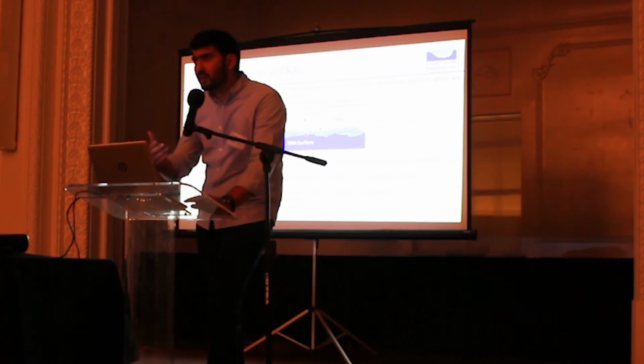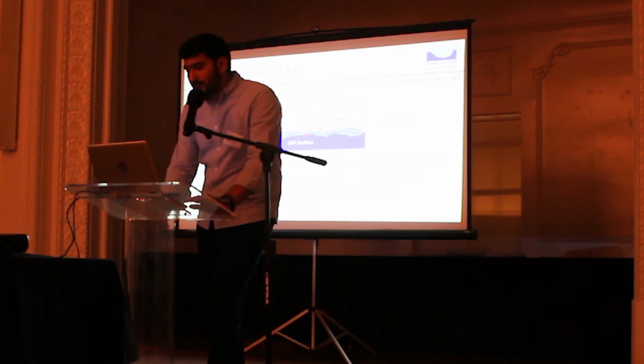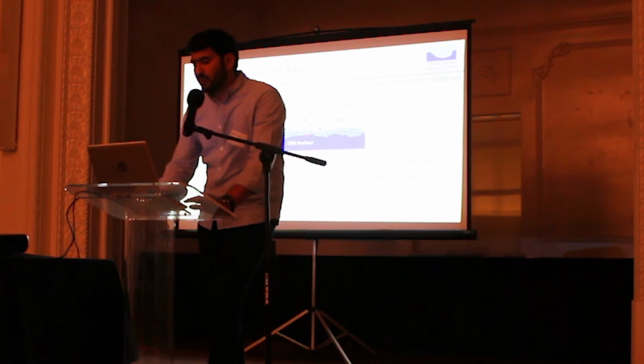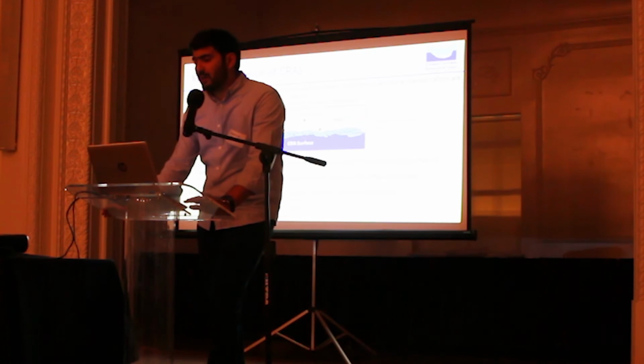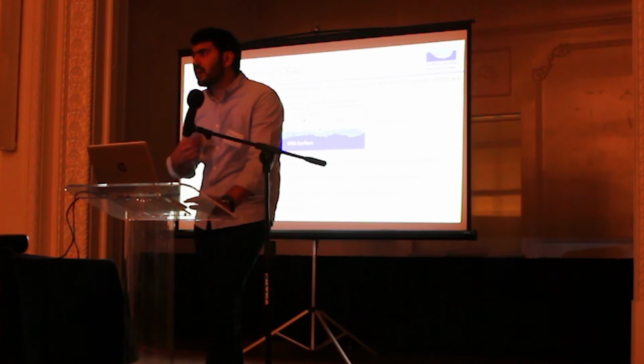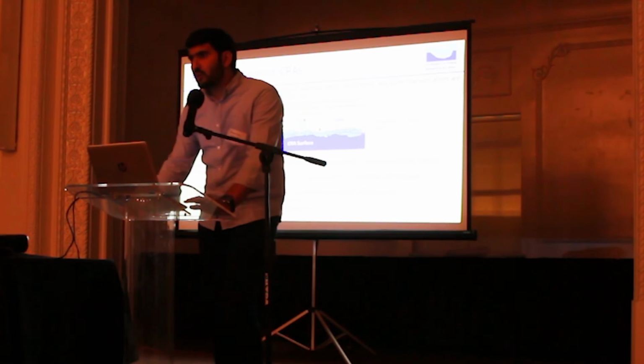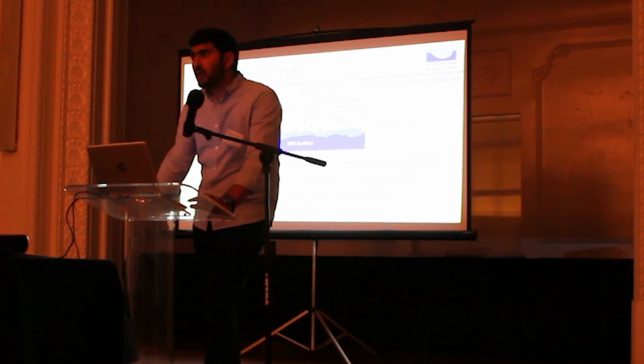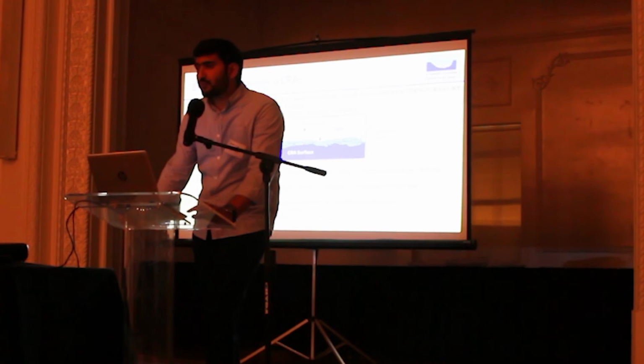In the presence of oxygen, there is a tendency for the passive layer, or the oxide layer, to repassivate and reform again while solid particle erosion is taking place, which suggests a synergistic effect between erosion and corrosion. In an oxygen-free environment, these oxide layers may not reform again. Also in salt water, we can have two competing processes happening at the same time. The chloride ion can break the passive layer, and the dissolved oxygen can work on the repassivation. So the question here is, is erosion corrosion a serious problem for CRAs in the oil and gas industry? And how erosive does the environment need to be for erosion corrosion to be a serious problem